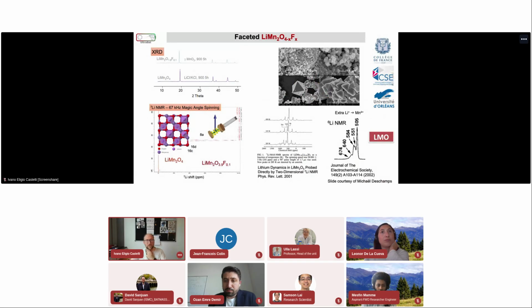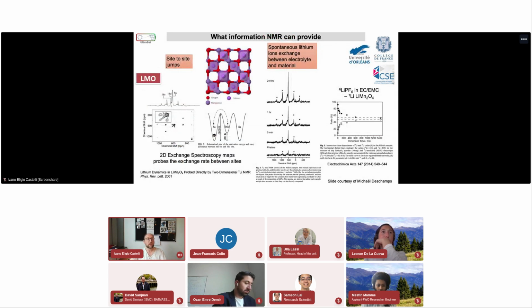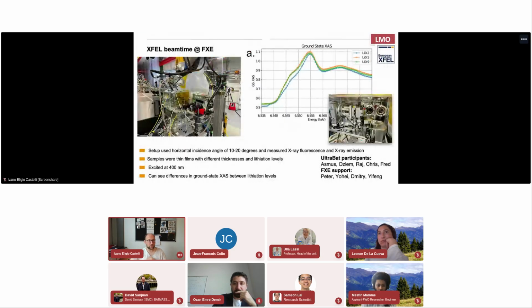And then it's important that we combine this information with experimental input. For example, we can get structural information from XRD. Here we use very pure, single-crystal samples and very accurate experiments, because we want to correlate very idealized experiments with a theory that is as good as possible, right? And we can look at where the peaks are in the structural information of the material during charge and discharge, at different lithiation stages, and then directly correlate it with the theory that we are developing. We have been at beam time a few times, which allowed us to really understand